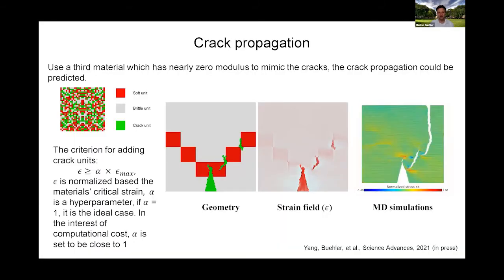Now, in this case, the evolution of the crack is predicted solely based on the stress field. And so we're truly replacing a simulation like a finite element simulation or molecular dynamics simulation and predicting which bonds will break because of the stress field distribution. So we have the whole picture now. And we have a second paper that we just submitted where we do systematic comparisons with continuum mechanics theory.